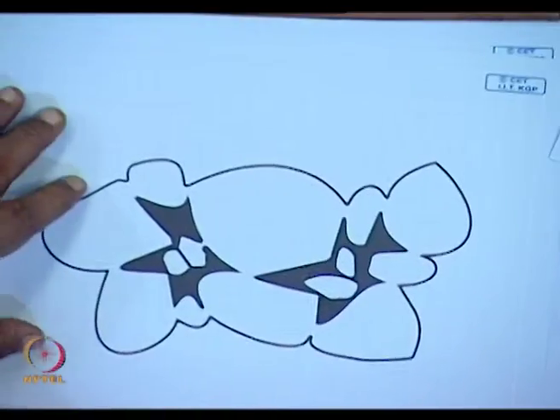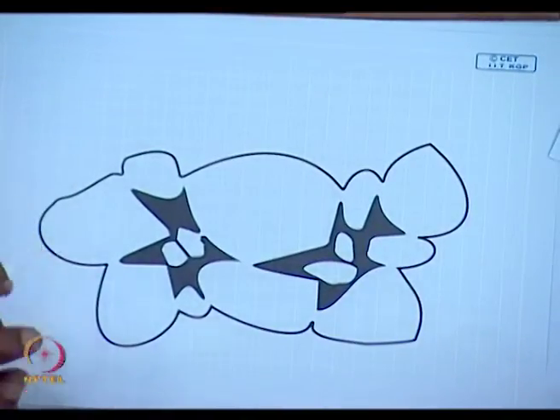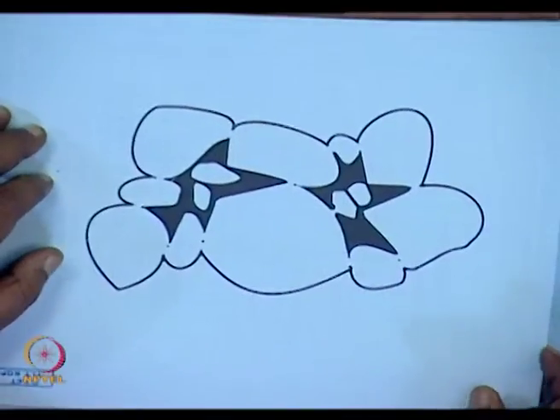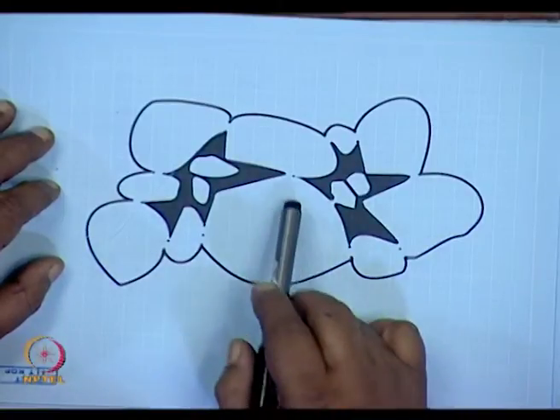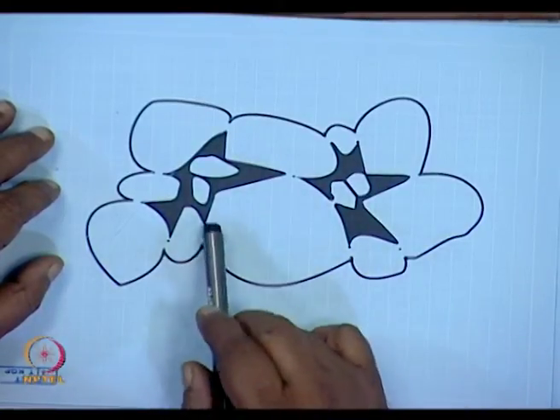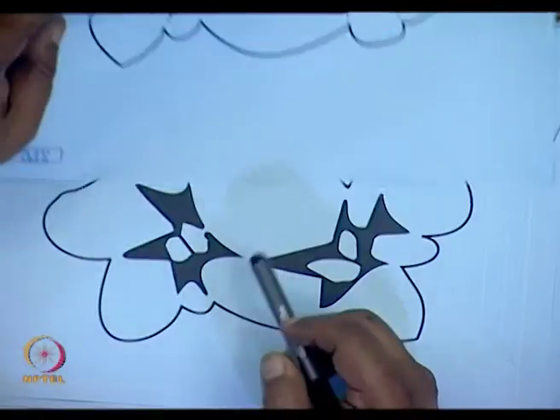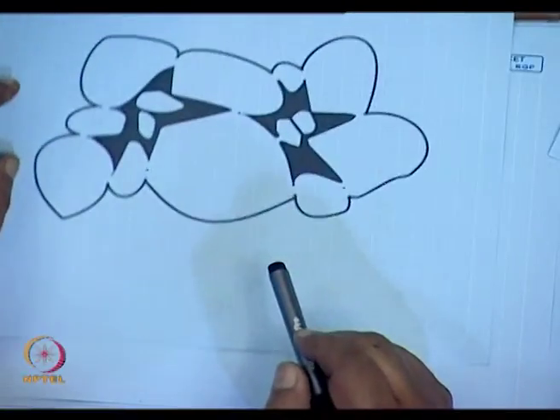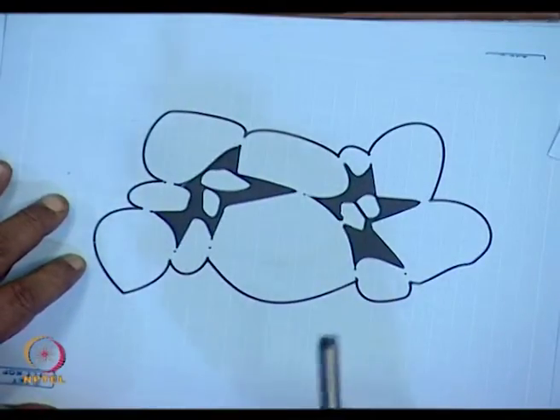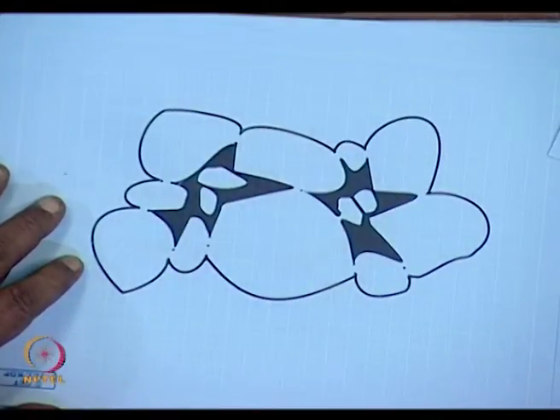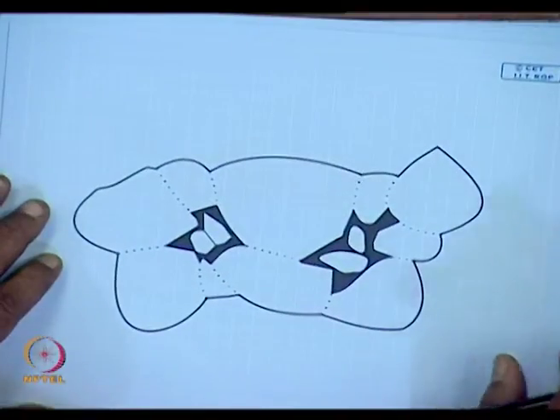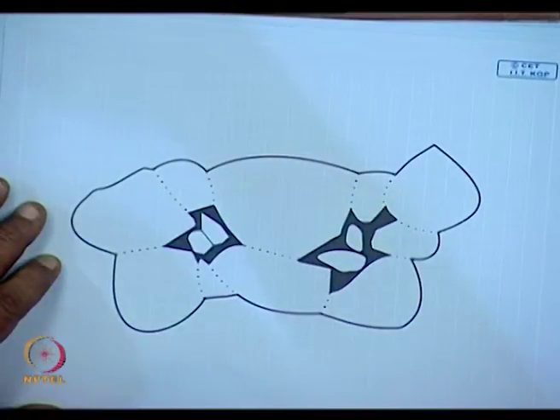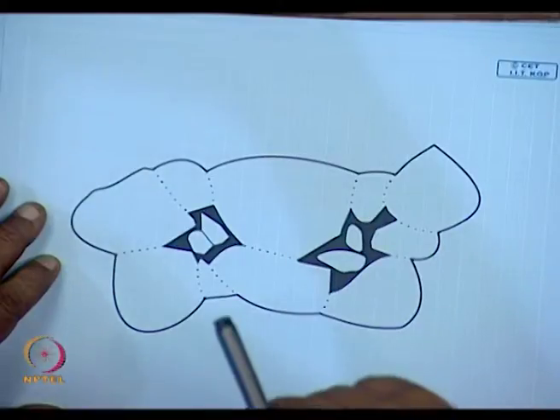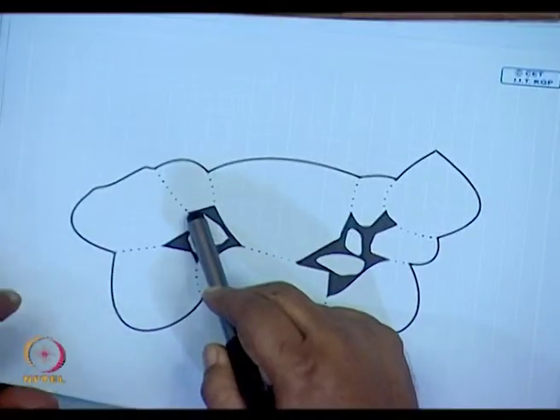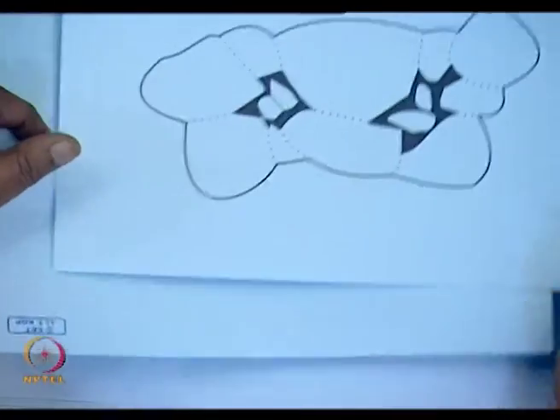If this was a diagram during the intermediate stage of sintering, as compared to the initial stage, what we are seeing is the necks have grown larger, grain boundaries have got lengthened, with a concomitant increase in grain boundary neck growth. A very large amount of neck growth with grain boundary lengthening has occurred over here as compared to over here.